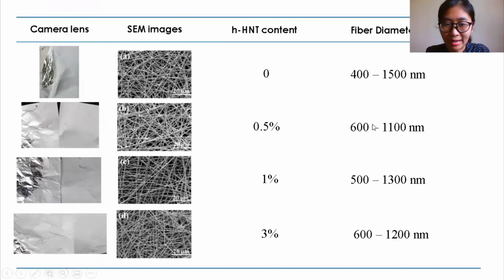Looking at the fiber diameter, the diameters reported here are shown as a ranged value because the determination of each fiber's diameter was done manually. But it was observed that increasing h-HNT content slightly decreases the mean average diameter of the composite fiber mats.